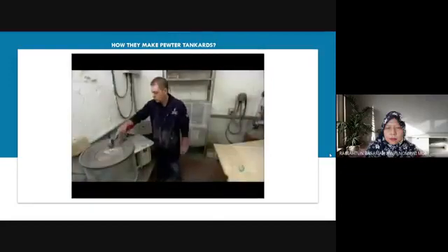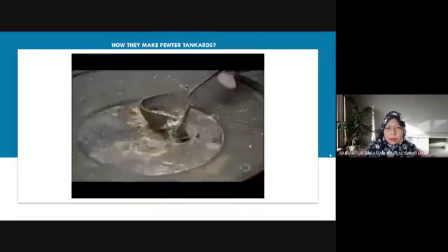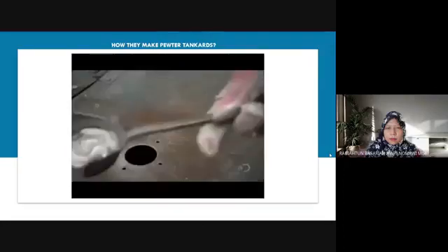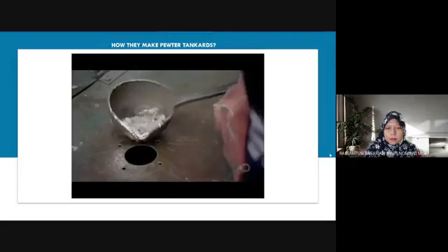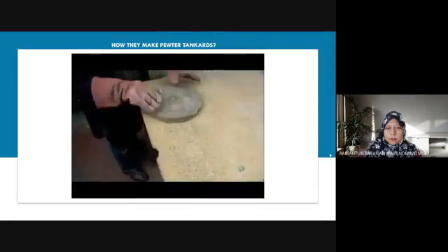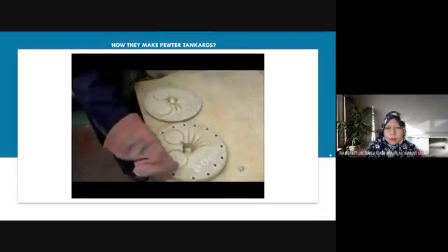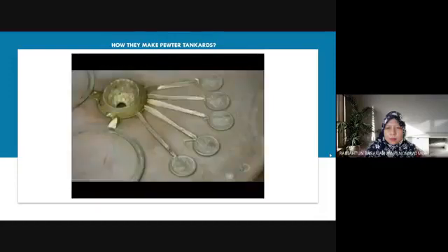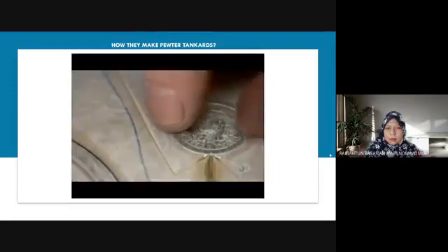Meanwhile, in the casting department, they heat solid pewter to 240 degrees Celsius, then carefully pour the now molten metal into a rubber mold. Inside are several cavities for spoons and large rings. After about 30 seconds, the pewter solidifies and the parts can come out.